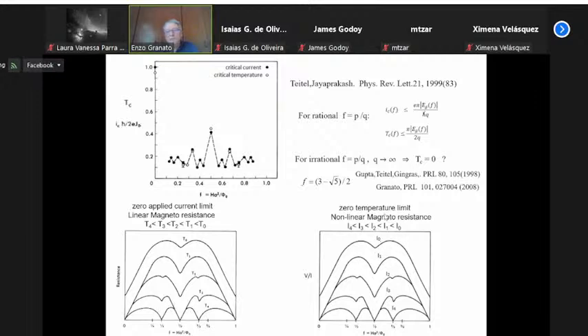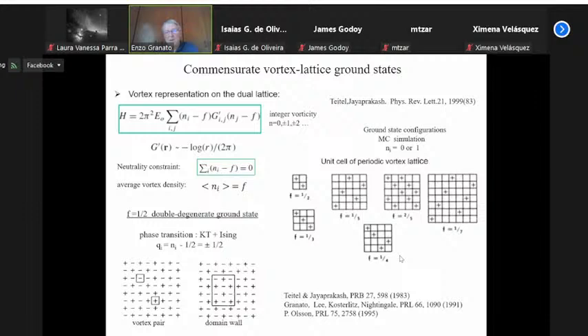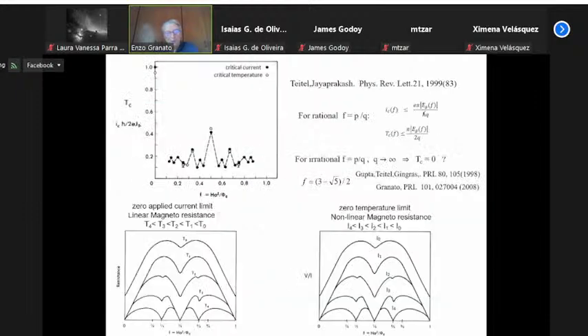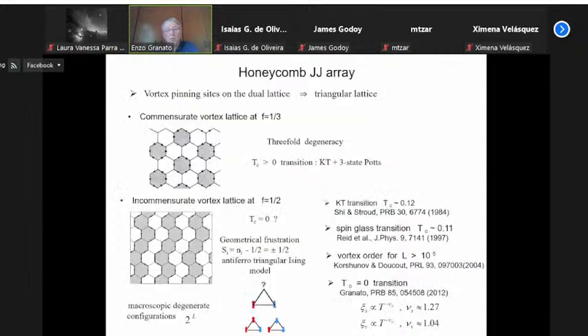The same thing happens if you are at zero temperature and you decrease the current from a large value. First, the voltage shows a minimum at the integer values, then at the 1/2 value, and so on. This particular picture is for the square lattice, but there is a strong dependence on the geometry of the lattice. For the honeycomb array, for example, the behavior at frustration 1/2 is very peculiar.